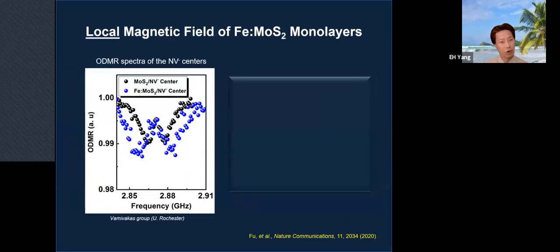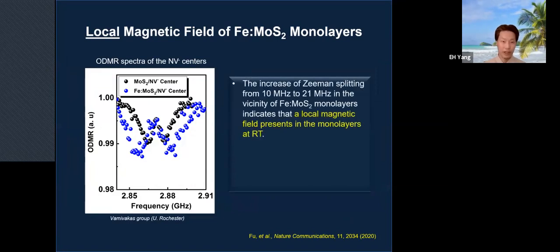We also measured the local magnetic field of this material, and we used the optically detected magnetic resonance spectra of the nitrogen vacancy centers. Basically, these nitrogen vacancy centers are defective nanodiamonds spun onto the surface of the sample here. And you see this data point in blue shows the increase of Zeeman splitting from 10 to 21 megahertz in the vicinity of the sample, which indicates that a local magnetic field exists in the monolayers.